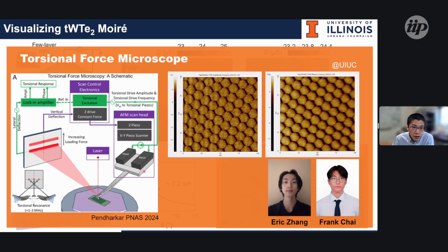We were able to image graphene systems very easily with a typical AFM tip. We now don't need to introduce any electrode to the system. We can image the Moire of the system, imaging many Moire systems just by detecting the AC friction of the 2D material. This method is called torsional force microscopy.